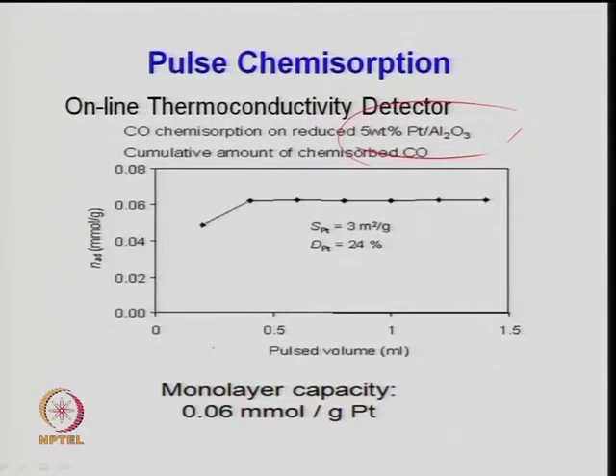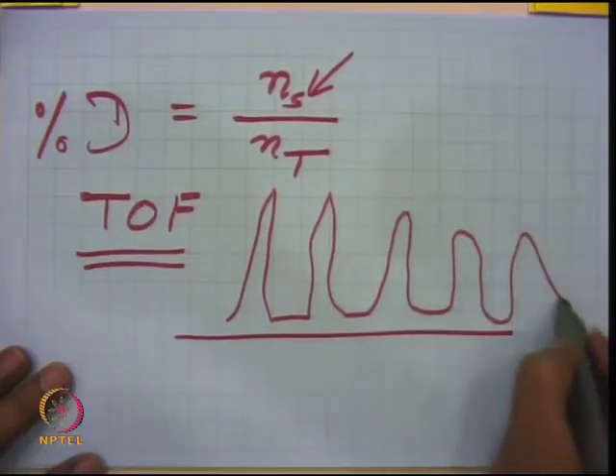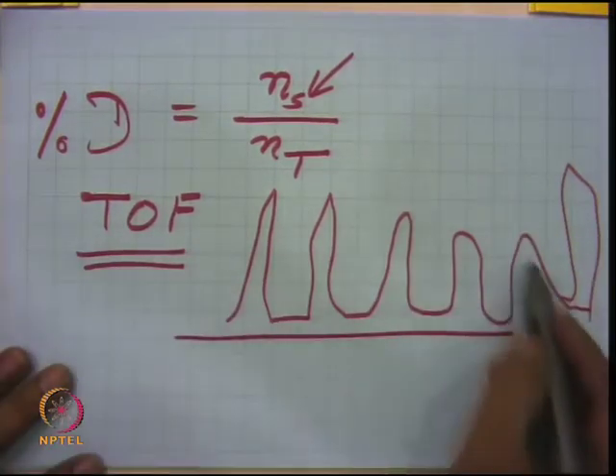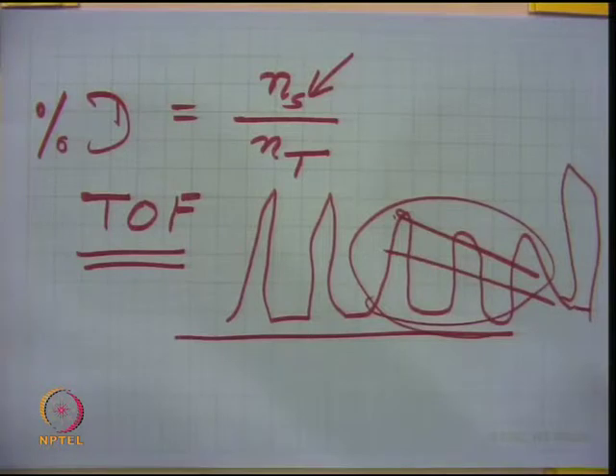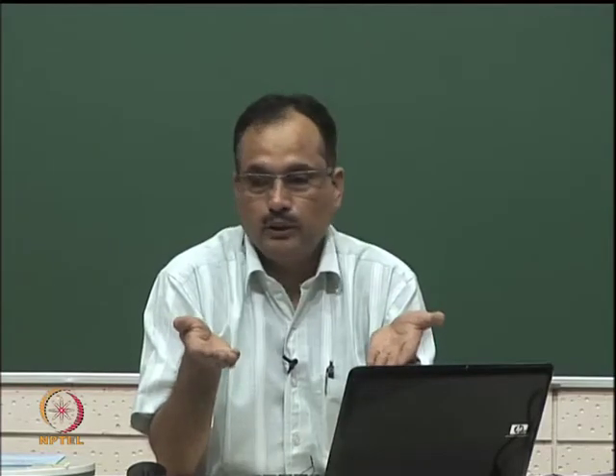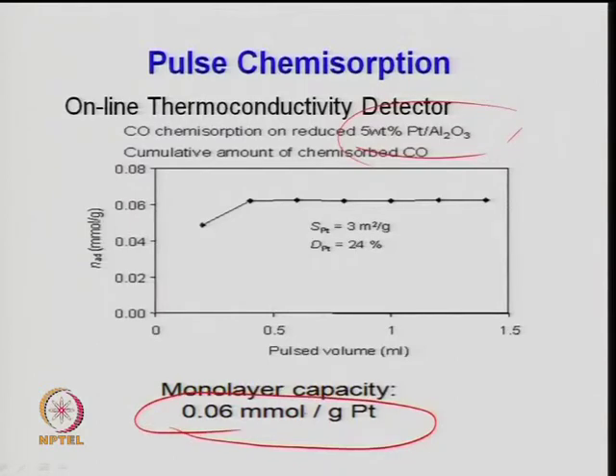Different volumes of pulses can be given and you measure the amount of gas chemisorbed until saturation. Initially if nothing is chemisorbing the pulse comes through fully, but as chemisorption takes place the signal decreases, and finally returns to its original level when saturation is reached. The decrement you observe across all pulses can be summed to find the millimoles of carbon monoxide adsorbed on the surface, giving the idea of a Langmuir-type monolayer coverage.